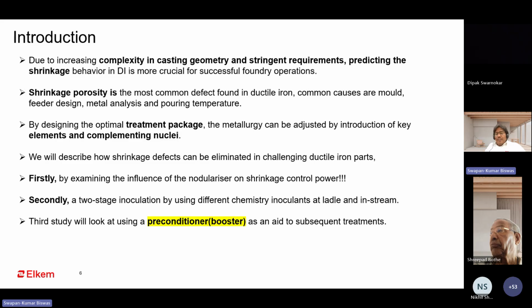In this presentation, I'll explain how the metallurgical defect is eliminated by changing the combination of raw materials, especially the alloy, magnesium, and inoculant. For shrinkage control, there is a lot of influence from the nodulizer, especially which type of ferrosilicon magnesium: normally lanthanum based ferrosilicon magnesium or the combination of lanthanum plus mischmetal. Selection of inoculation is also very important to control micro shrinkage in ductile iron. And in my study, I also explain the effect of preconditioning. We can call it a booster for the liquid metal for improving quality.